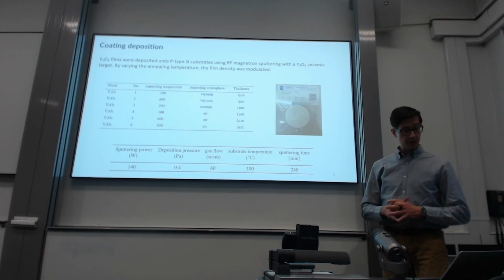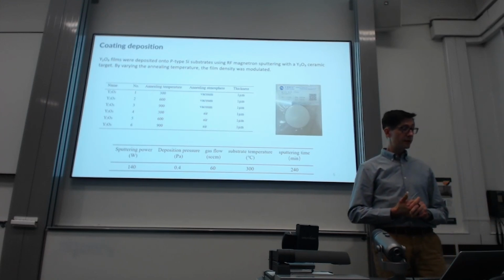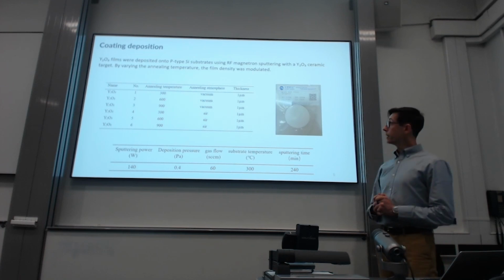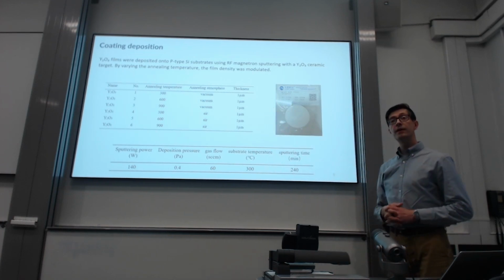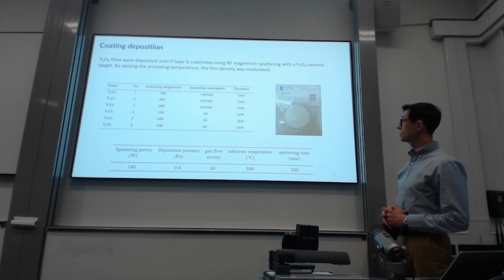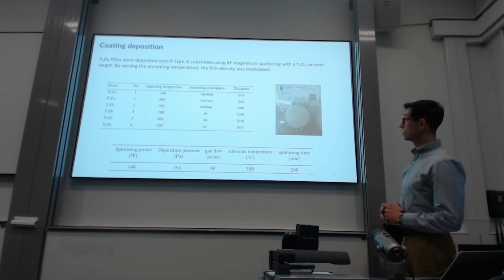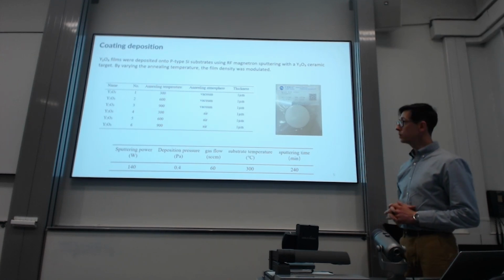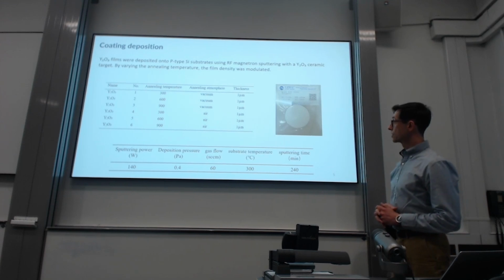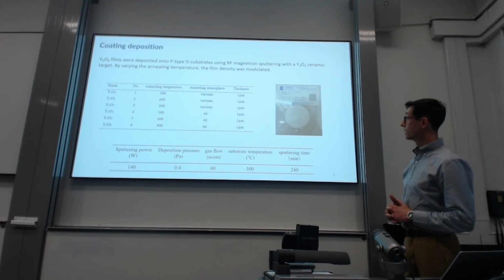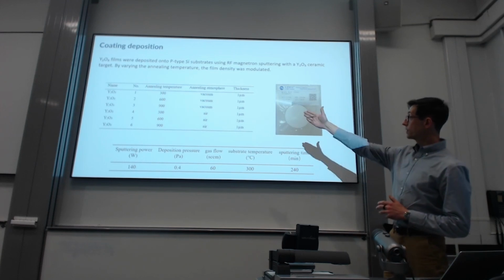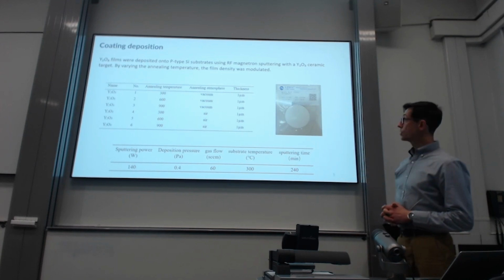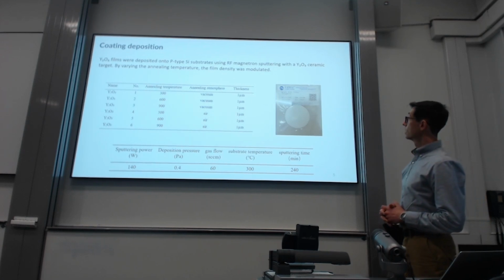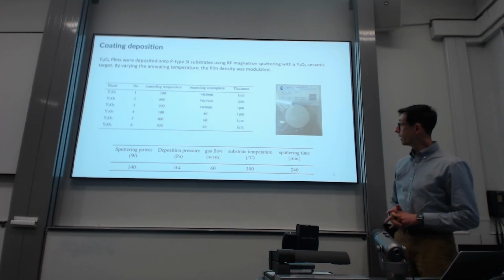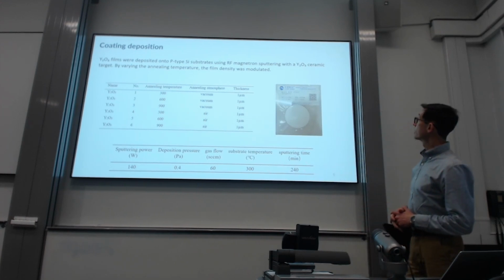So coatings were deposited by radio frequency magnetron sputtering, and you see the table with all the 6 variants that we deposited and investigated in this work. So basically what you need to remember is that we looked at 2 different annealing atmospheres. The first 3 samples were annealed in vacuum conditions, and samples 4 through to 6 were annealed in air environment. And between those 3, there is a difference in annealing temperature, 300, 600, and 900 for those variants. And the deposition conditions are listed here.